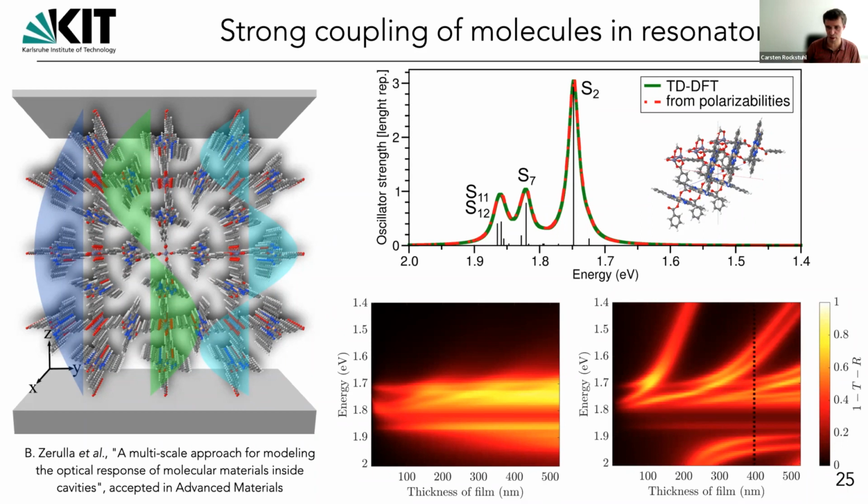Maybe worthwhile to mention, the experiment to which we have been referring in the simulation studied the absorption in the system for a film thickness of 400 nanometers, and it had been experimentally identified. At the spectral region where there's a single absorption line here, if you couple to the modes in the cavity, you are going to see a strong absorption line here and a strong absorption line here.